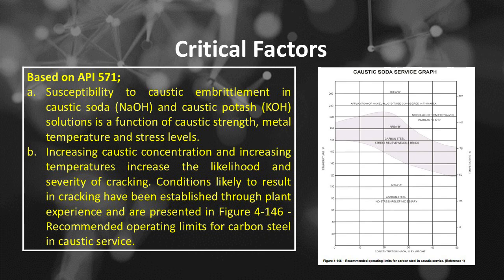Caustic stress corrosion cracking, caustic embrittlement damage. Critical factors based on API 571. Number A, susceptibility to caustic embrittlement in caustic soda and caustic potash solutions is a function of caustic strength, metal temperature, and stress levels. Number B, increasing caustic concentration and increasing temperatures increase the likelihood and severity of cracking. Conditions likely to result in cracking have been established through plant experience and are presented in Figure 4-146, recommended operating limits for carbon steel in caustic service.